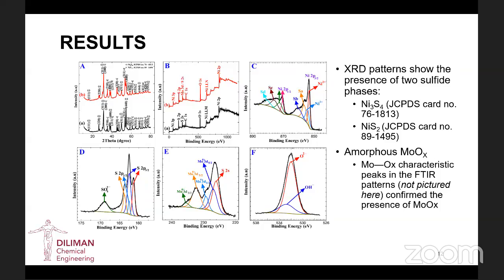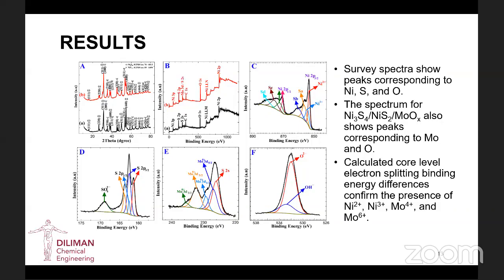But we conducted an FTIR study and compared the results with previous studies to also confirm the presence of molybdenum oxide. And then we have XPS, where we got the survey spectra showing peaks corresponding to nickel, sulfur, and oxygen. And for the material with molybdenum, there is an additional peak in letter b showing molybdenum 3d and sulfur 2s. I will not be discussing this in detail, but the results further confirm the presence of nickel 2+, nickel 3+, molybdenum 4+, and molybdenum 6+, based on the calculations done for the binding energy differences of the high resolution spectra for nickel, molybdenum, and sulfur.